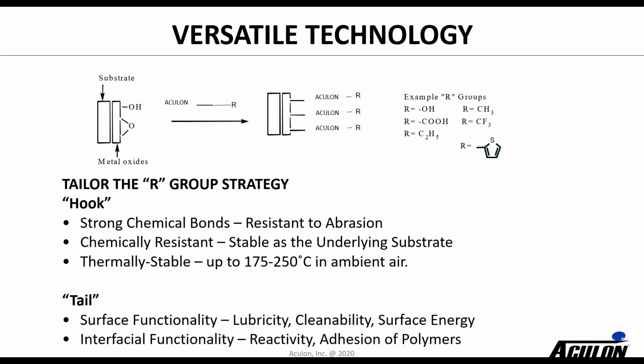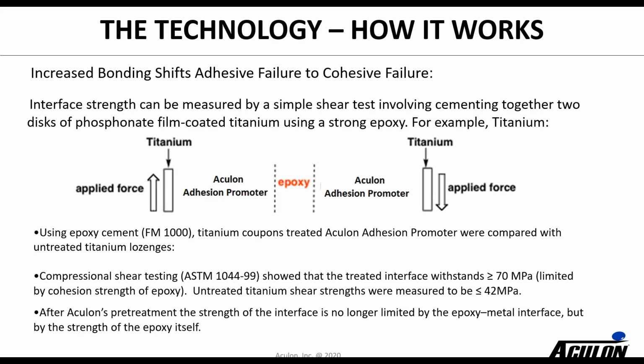We also do a lot of repellency treatments, whether it's lubricity or making things easy to clean or just changing the surface energy. This tail allows us to really change the functionality. And for adhesion, it's really the importance of getting a good interface between what's being bonded to the substrate. And then the treatments are generally pretty thermally stable. Most of them are stable up to about 200 C.